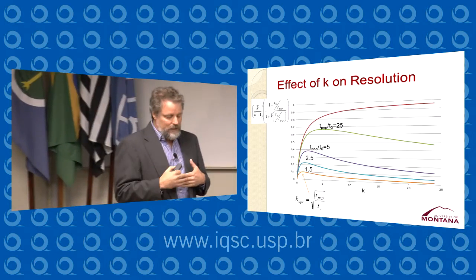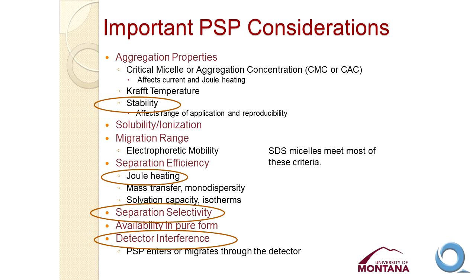And so Joe Davis has published a series of papers in which he has demonstrated that it is this Joule heating effect with SDS micelles that limits the efficiency of the separations in electrokinetic chromatography. Separation selectivity is not a problem with SDS, but SDS provides only one separation selectivity. So it would be like trying to do gas chromatography and having only one stationary phase, or doing liquid chromatography and having only one stationary phase. So it's nice to have different stationary phases to give us different selectivity.